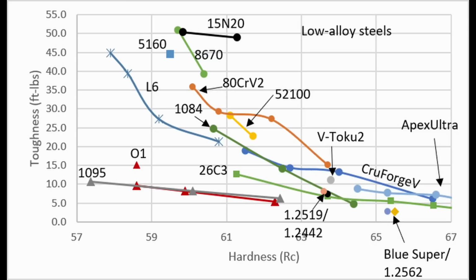And just like we saw with 4340, the best way to ensure that a steel has high toughness is to have lower carbon. So if you can get 54 Rockwell with 40 points of carbon, that's probably going to give you higher toughness than tempering a high carbon steel down to that hardness. And so 15N20 and 8670 seem to be able to make up for their little bit higher carbon than 5160 through the addition of nickel. So it does seem like nickel is having a positive effect on toughness.